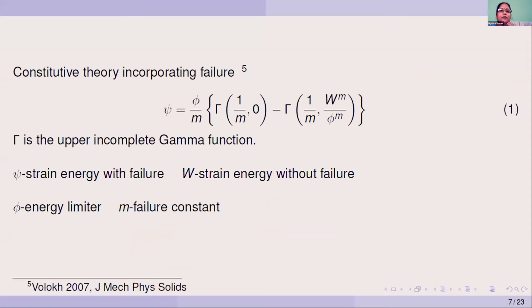So here we formulate an expression for the strain energy density function to enforce material failure description. Here this phi is the energy limiter, which is as discussed before, and this gamma is the upper incomplete gamma function, and this W is the strain energy density to describe the intact material behavior without failure, and this M is the model parameter which controls the sharpness of transition to failure on the stress strain curve.